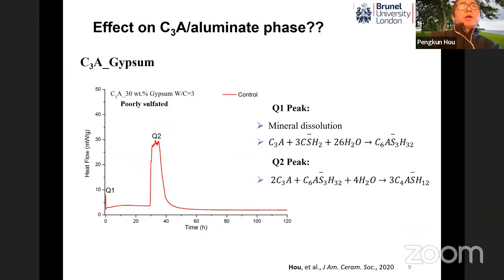So there comes the question: what's the specific effect of nanosilica on the aluminate phase? To do that, we designed a system consisting of C3A and 30% of gypsum, which is actually poorly sulfated. And we can see two distinct peaks. Q1 represents the hydration of C3A with gypsum forming AFt. And then Q2 is after depletion of the gypsum, the transformation of ettringite to AFm.